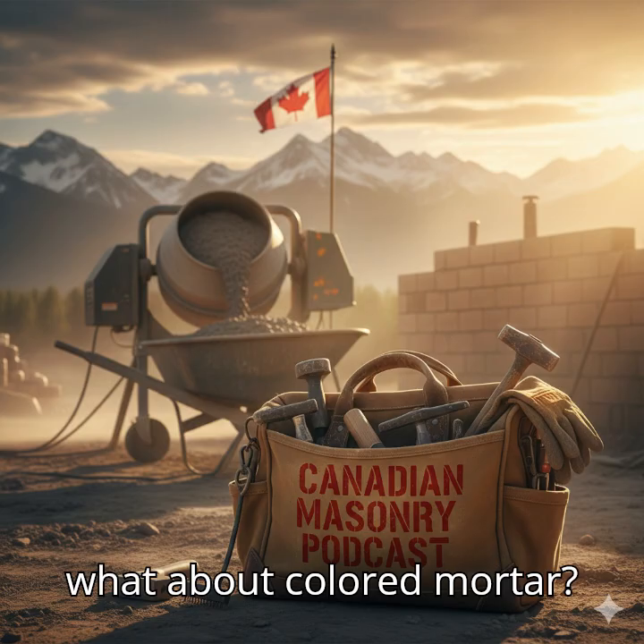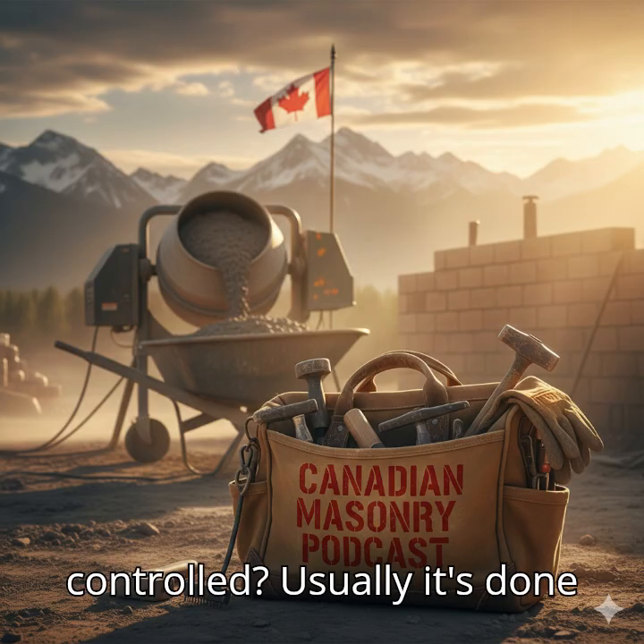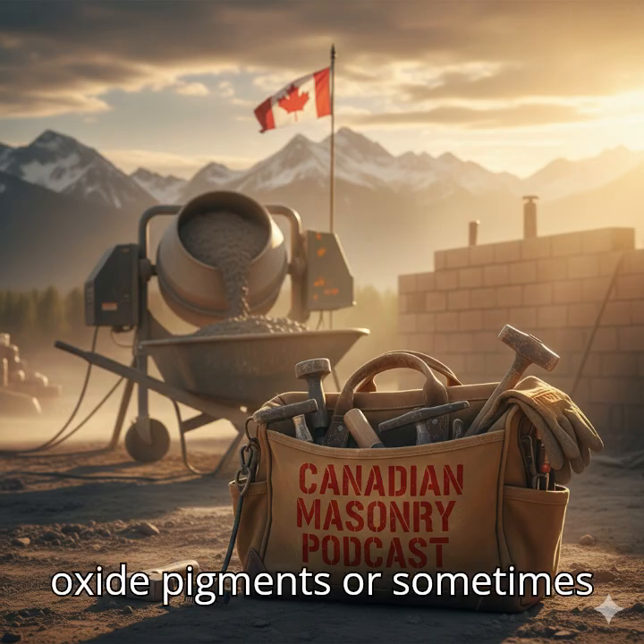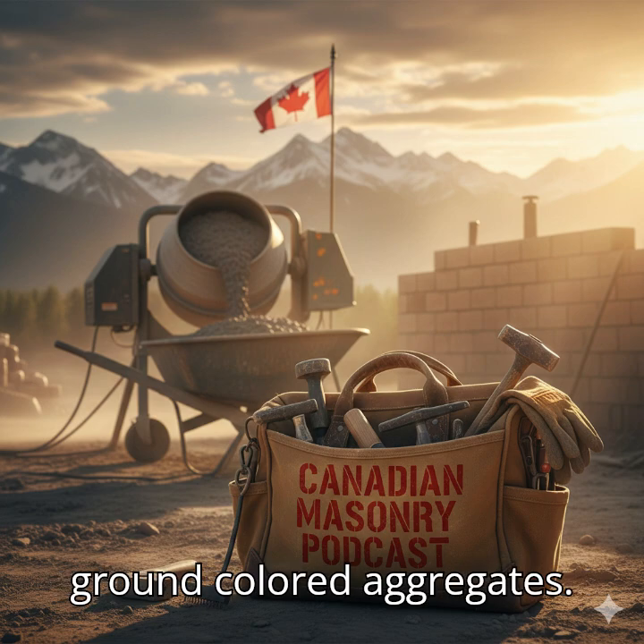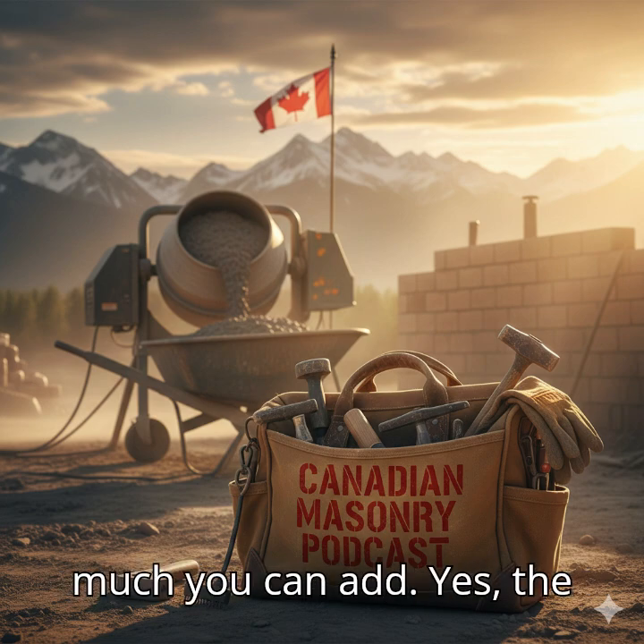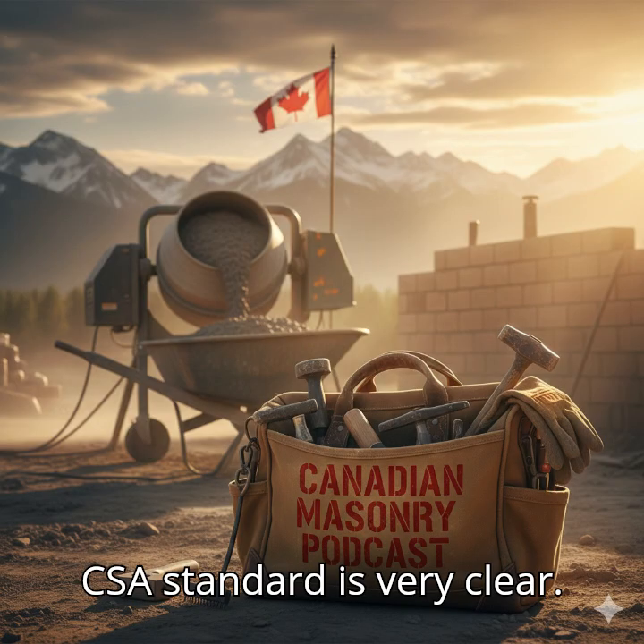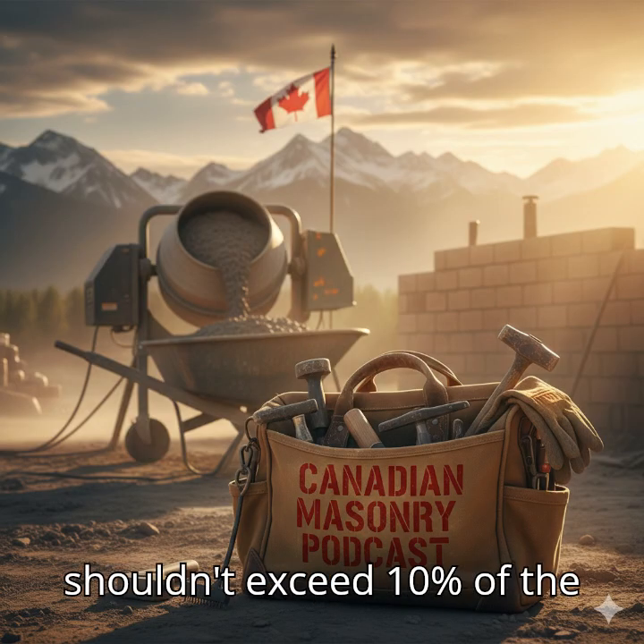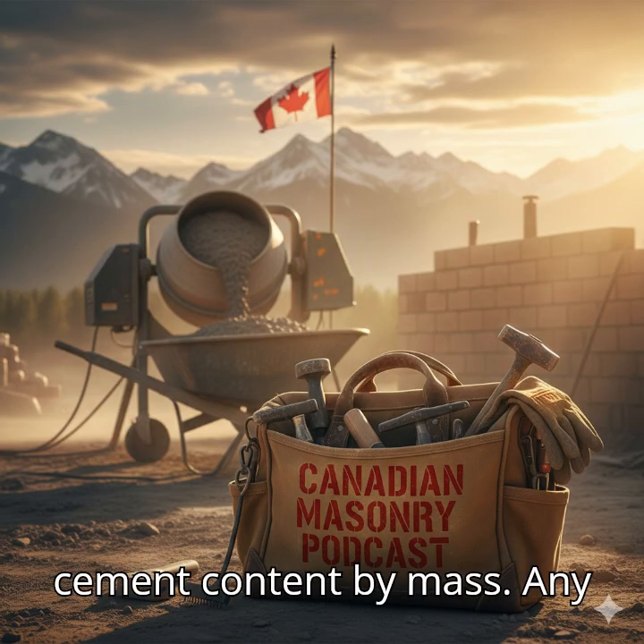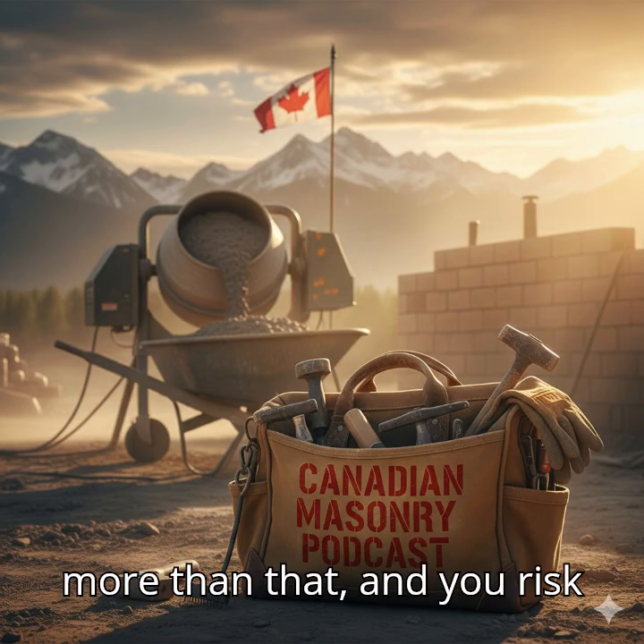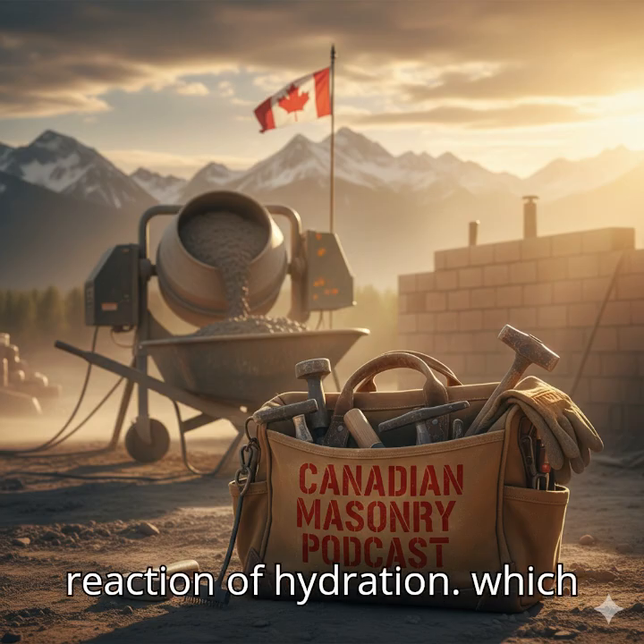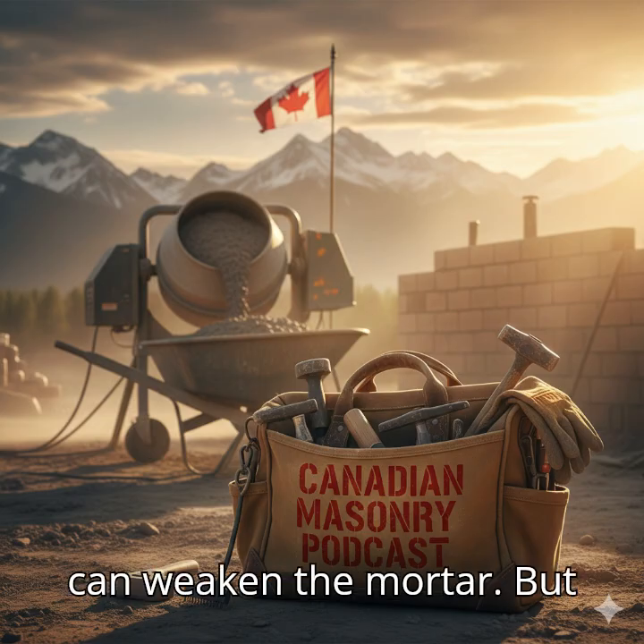So what about colored mortar? How is that achieved and controlled? Usually it's done with highly stable metallic oxide pigments or sometimes ground-colored aggregates. And there are limits on how much you can add. Yes, the CSA standard is very clear. The coloring admixture shouldn't exceed 10% of the cement content by mass. Any more than that, and you risk interfering with the chemical reaction of hydration, which can weaken the mortar.